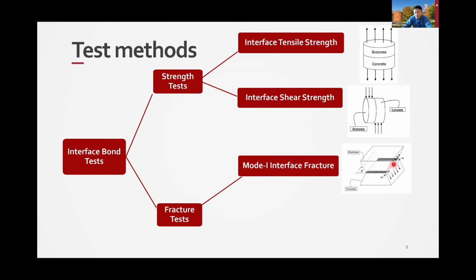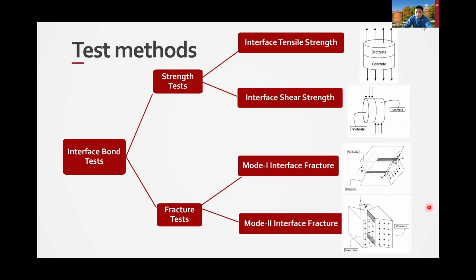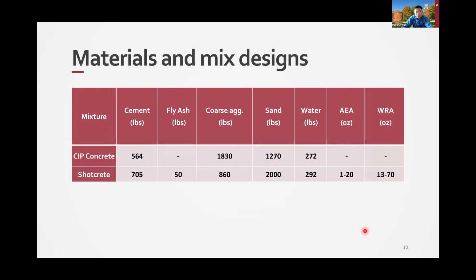For the mode one test, you'll be pulling with the crack notch already in place. That's the mode one test. And then you have mode two, where you will be doing the shear test instead of tension. That's the mode two fracture mechanics test. These are the materials we used in this study. You have the existing cast-in-place concrete, and then the shotcrete mix design. These are from previous studies that came up with these two mix designs.